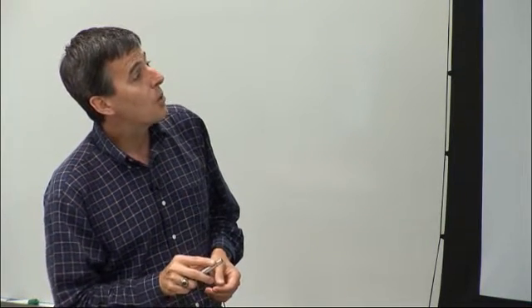Here's an example. So this is a very thin plate of silicon. We've printed it down onto a micro-machined ridge on a plastic sheet. There's no adhesive at all right here. This is just van der Waals forces keeping it in this cantilevered state, partly because of that scaling. So thin silicon is what we like. It's floppy, it's very flexible, and it's sticky in some sense. So you can do this kind of heterogeneous integration. So those are nice features.